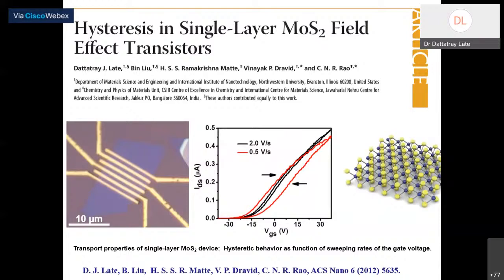They are coming and they functionalize these materials, because nowadays the material is naturally highly sensitive, right? They start connecting all these materials with oxygen functionalization, water molecules, and all these things, and that way the materials start slowly degrading. So we need to put a kind of protective layer. Once you have that layer, you will not get the hysteresis in your devices.